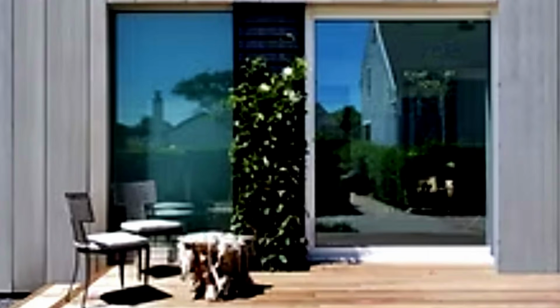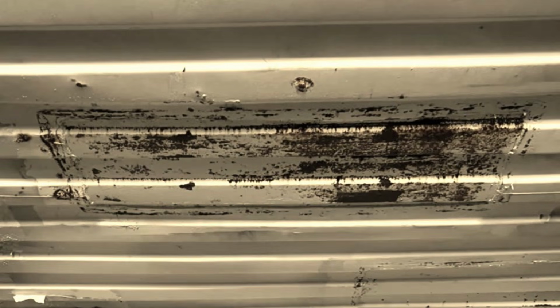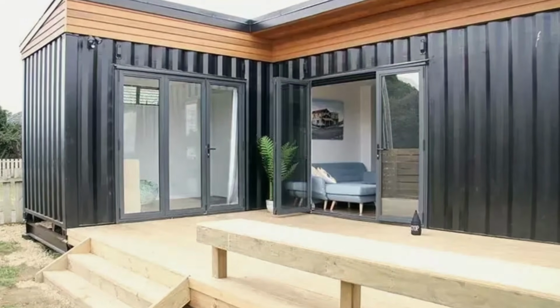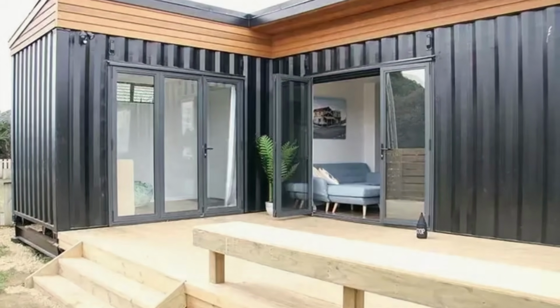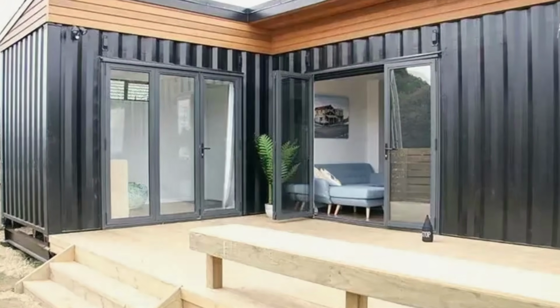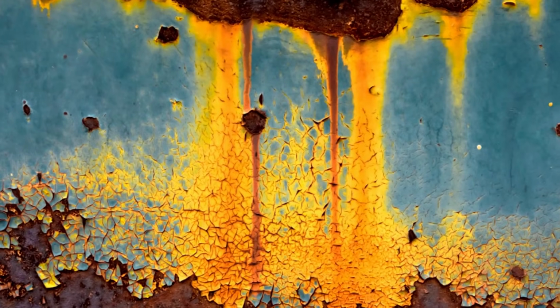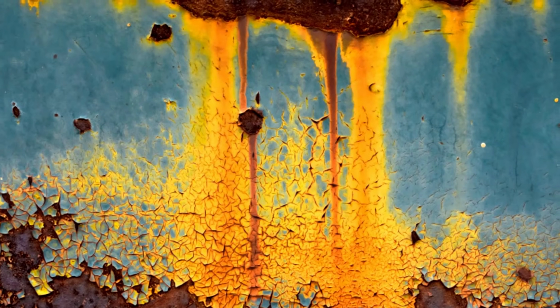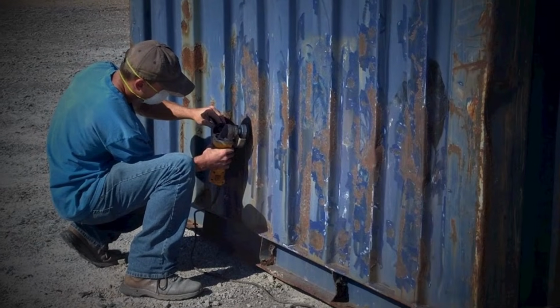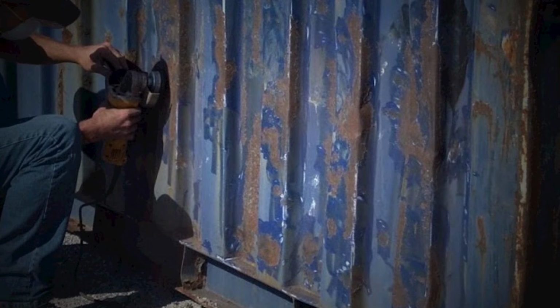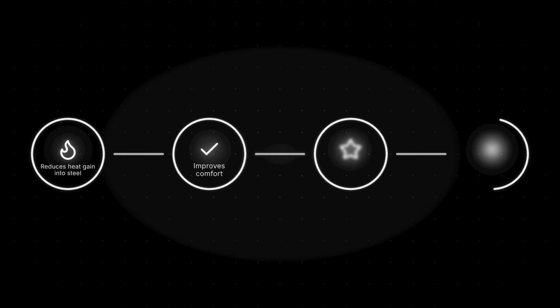Now, the honest limitations, because I'm not going to stand here and tell you this is a miracle product with no downside. First, surface prep is not optional, and it's the part people try to skip. If you coat over active rust or failing factory paint without removing it first, the new coating will look fantastic for 6 to 18 months and then start to bubble, flake, and fail from underneath, because the bond was never solid to begin with. This is the single most common reason people report disappointment with elastomeric coatings, and it's almost always a prep failure, not a product failure.